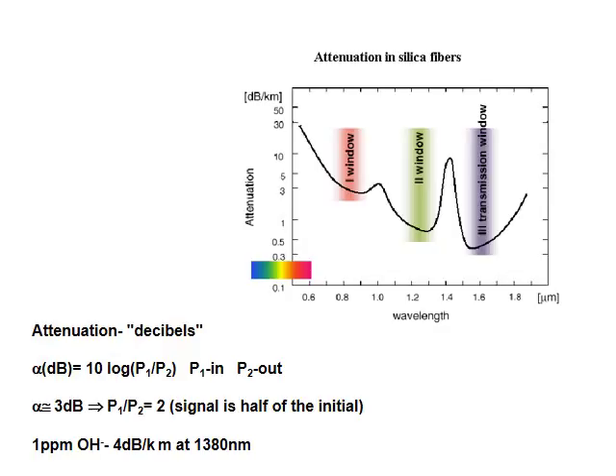1 ppm of OH in silica fibers leads to 4 dB per kilometer at this wavelength. New methods of fabrication of fibers claim to remove these residual OH groups. Coming back to the spectrum, you see that for 1 centimeter of optical path, absorbance of silica glasses in the visible range is 5 times 10 to the minus 5.